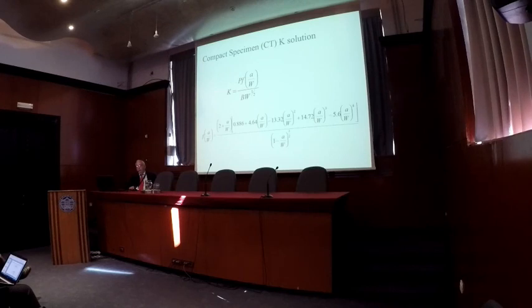Examples of K solutions that you can find. This is a compact specimen, and I'll show you that geometry later. But load, this is thickness out of the plane, that's the planar dimension, and this is a function that depends on the crack length to width ratio. Now that function is somewhat complicated. Wednesday I'm going to show you an easier way to do that when I give a plenary lecture, but for now, this is the thing that's in most of the standards that calculates a K for that compact geometry.